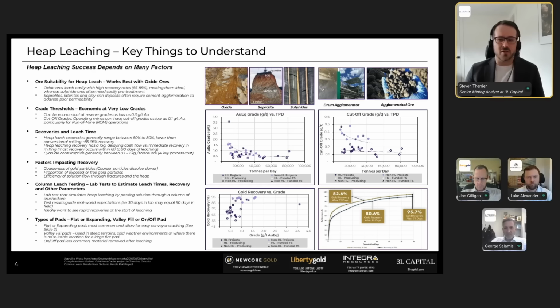So what is agglomeration? Basically mixing that ore with cement and turning finer particles into larger stable aggregates, and that enhances the solution flow through the pad. And you can also overcome that by mixing clay-rich zones with less clay zones if you have those.